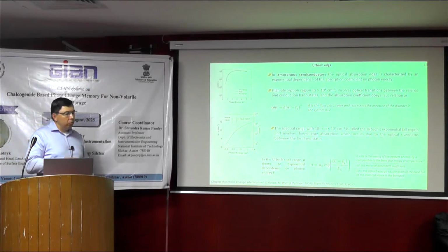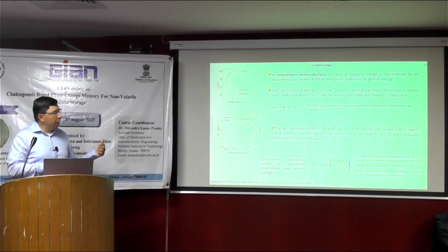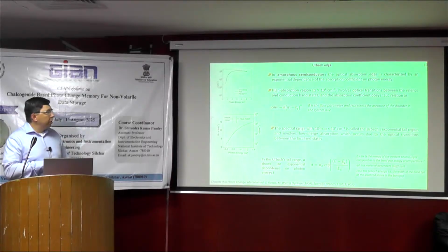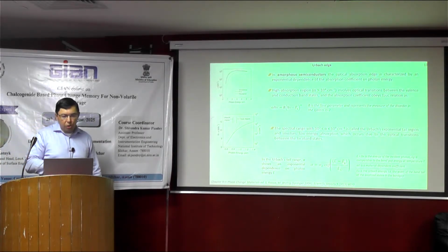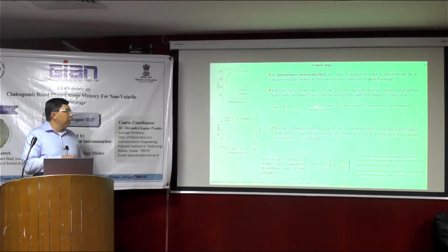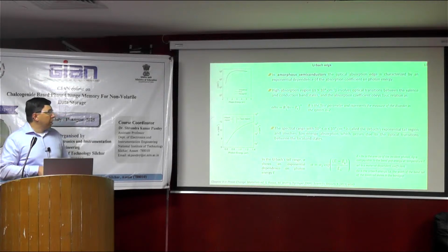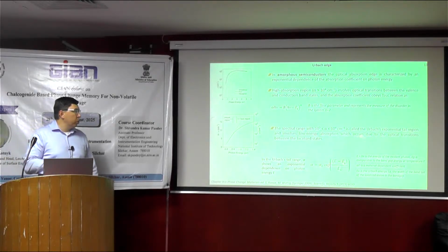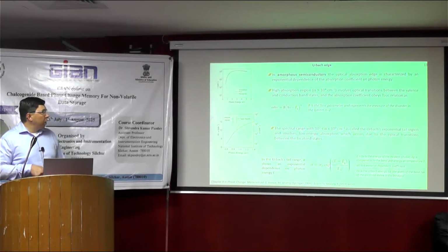Here, by measuring the optical band gap, it was a constant, but in this case this is B, which is the Tauc parameter, and it represents the measure of disorder in the system. And this exponent is equal to 2. In the spectral region between 10 to the 2 and 10 to the 4, it's called the Urbach exponential tail region, and it involves low energy absorption, which occurs due to optical transitions between the localized states.